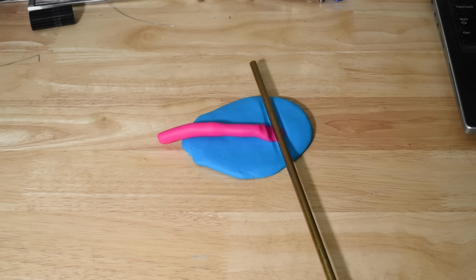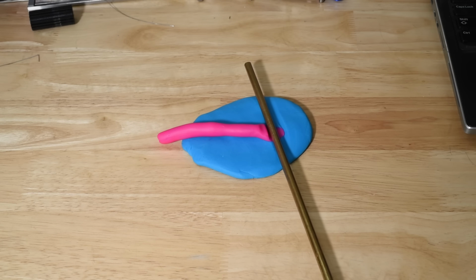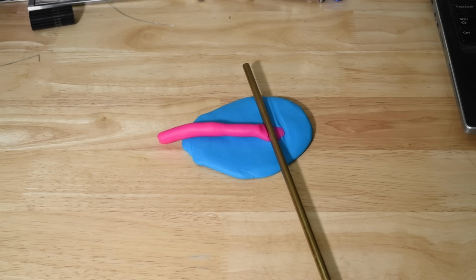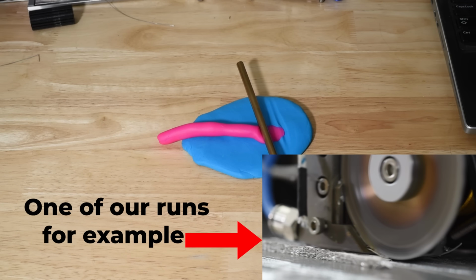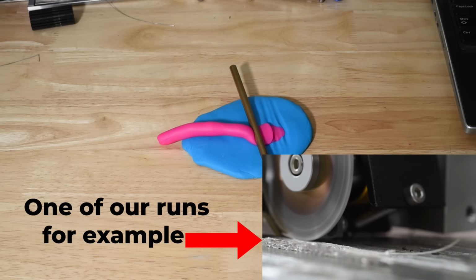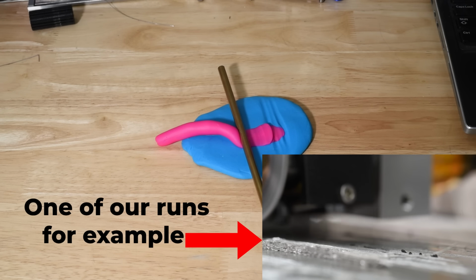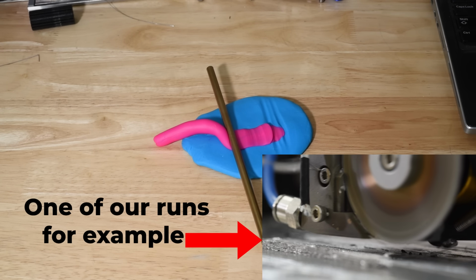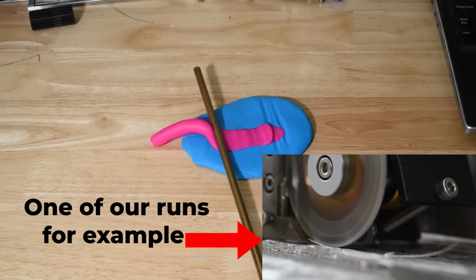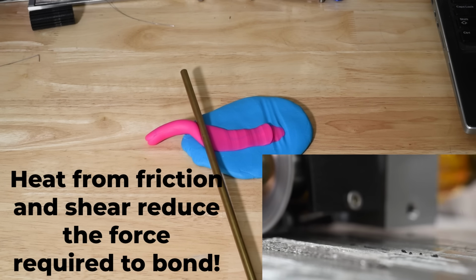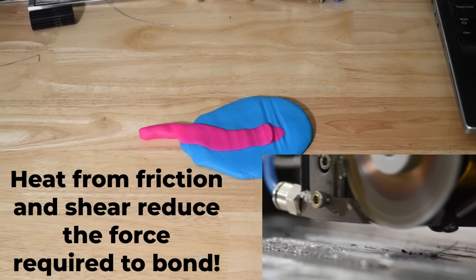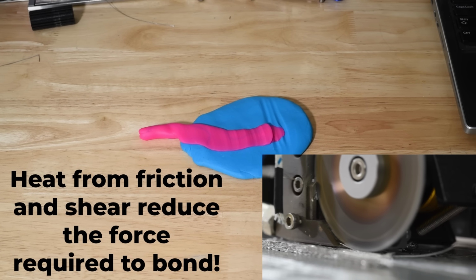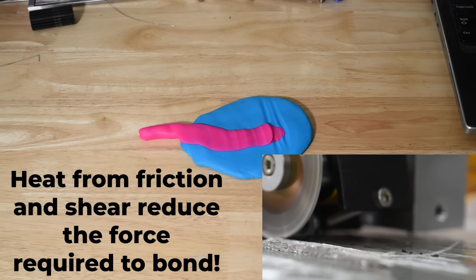what we're instead going to do is very gently place our shear tool, in the case of Rotoforge, our wheel, and get it very close to our substrate, and then we're going to feed into that some of our feedstock. And then when we apply shear, we locally deform the feedstock, and using very low force, we can shear it into the substrate, and we can locally mix the feedstock and the substrate such that we can get strong bonding between them. In the case of aluminum, we can shear their lattices together to essentially produce a bulk aluminum part.